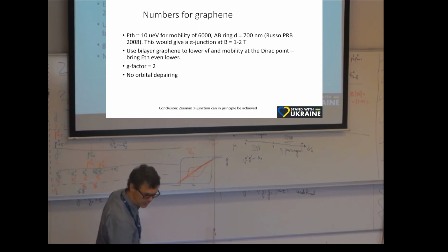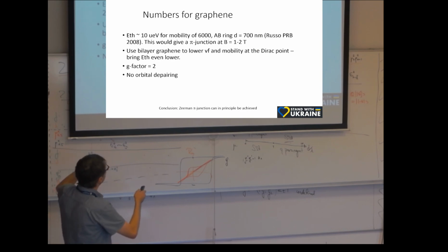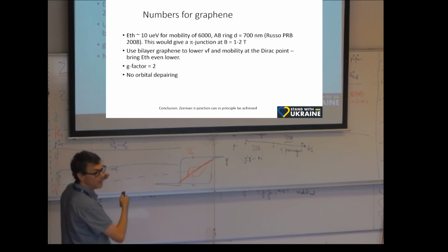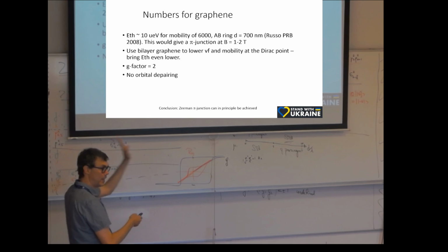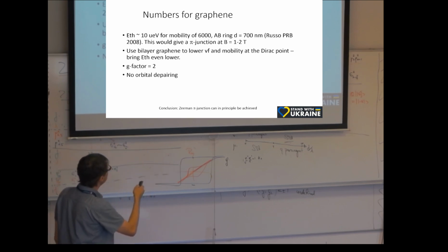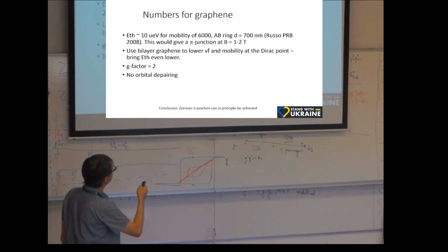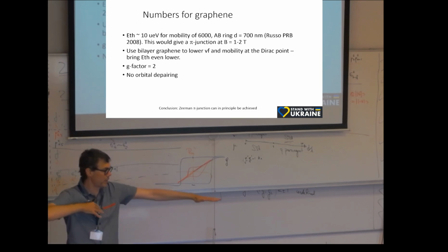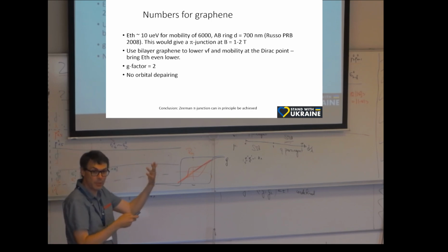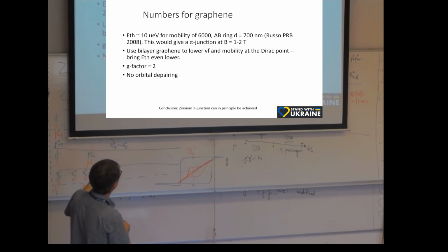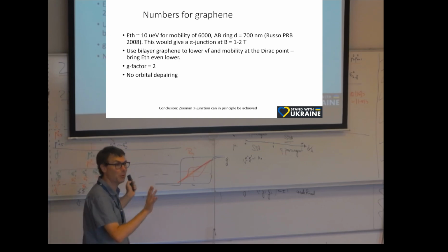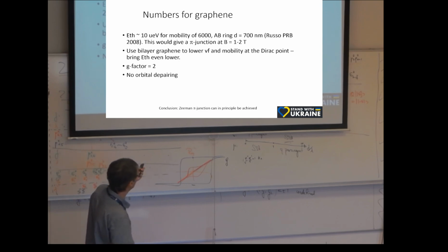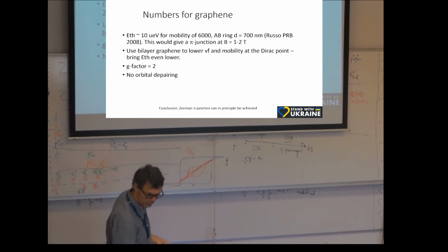Absolutely. That's the idea, right? So here are some numbers. On the one hand, the bad thing about graphene is the G factor is 2, like free electrons, so you have to go to pretty high fields. It's a pretty clean material, so the mean free path is long, and that means the Thouless energy is typically large. So you have to make a very wide junction, with two superconductors far apart. These are the kind of heuristics I was using, with a very thin thickness. I wrote no orbital depairing. I no longer believe that, so it's not correct, but I wrote no orbital depairing. But I need to go to 1 or 2 Tesla. I need the superconductor to survive to high fields. So that's kind of the game.